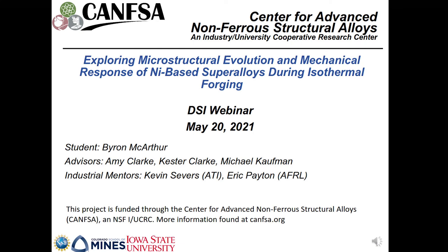For Brian Allen's question about the connection between superplasticity and that transition in abnormal grain growth, I think in this temperature regime you're having this partial dissolution of some of the primary gamma prime, and this is how you get, I wouldn't say bimodal, but a grain size distribution of the gamma, and this partially leads to some of this inhomogeneous stored energy distribution within the material.